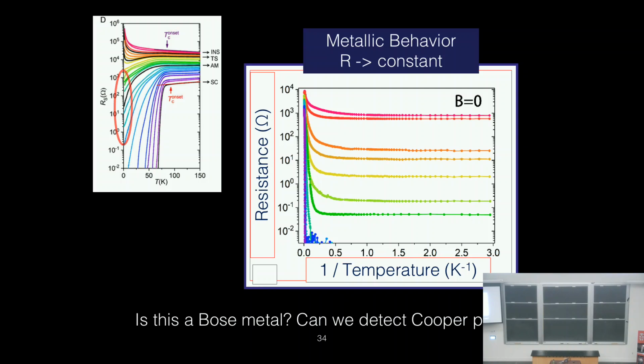And if you look way down here, and now we're going to plot the resistance versus 1 over temperature. The resistance drops and then plateaus to a finite value. Less damage, it plateaus to a lower value. But the resistance becomes temperature independent at low temperatures. That's a real sign of a metal.